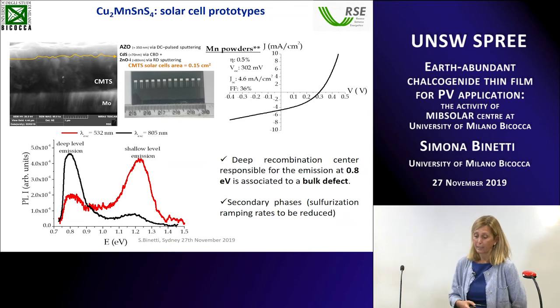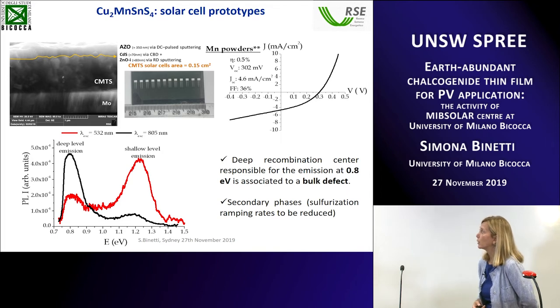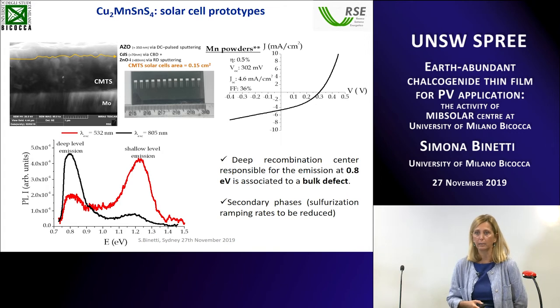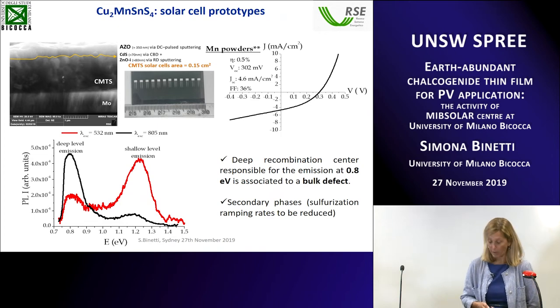Also in this case, like in the case of Kesterite at the beginning, we found a lot of deep recombination centers detected by PL at a lower energy, and maybe related to the presence of secondary phases that were detected by Raman and by X-ray diffraction.